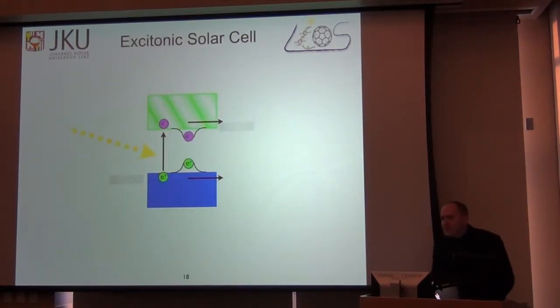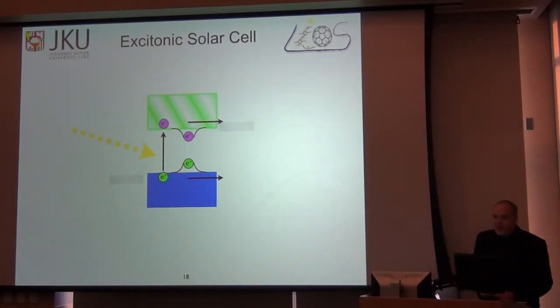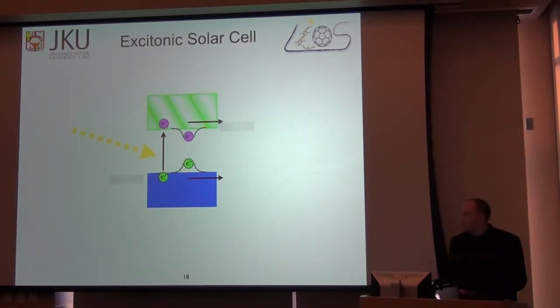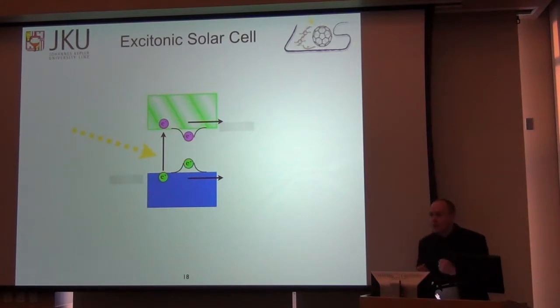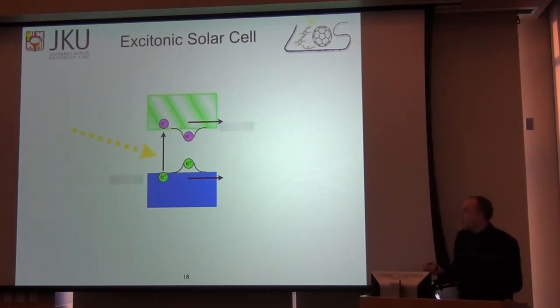But with organics, we have a slightly bigger problem. When we shine light in, we don't generate free carriers. We have an extra loss mechanism. We promote an electron from the HOMO level to the LUMO level, but that is immediately formed into a tightly bound exciton on the order of 100, 200 meV binding energy. So it's much higher than thermal energy. We can't dissociate them easily. We need some external process.